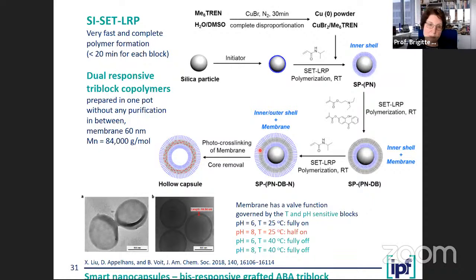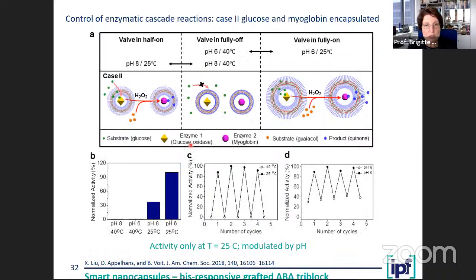It contains a pH sensitive as well as a temperature sensitive material. And you can control now the diffusion by both pH and by temperature. And that's shown here. We always show that the diffusion works and we can control it by encapsulating enzymes. The enzymes allow us to follow if it works or not and how is the pH dependency. And I hope you see that we have on the one hand pH dependency, shown here, but we also have the temperature dependency from the both components in the shell which we used for our capsules.